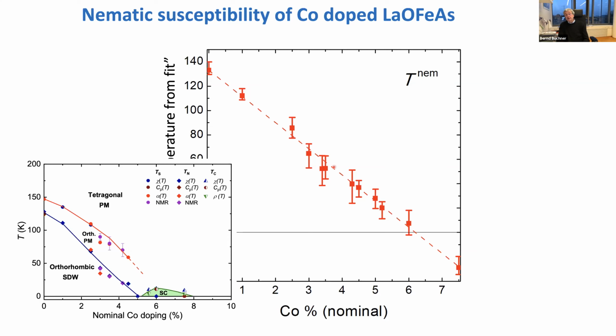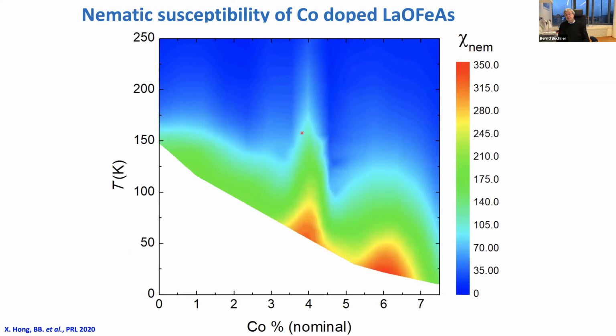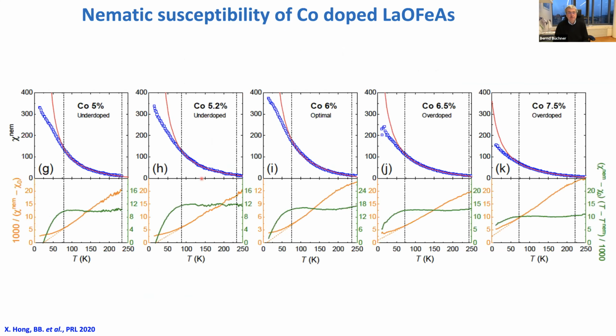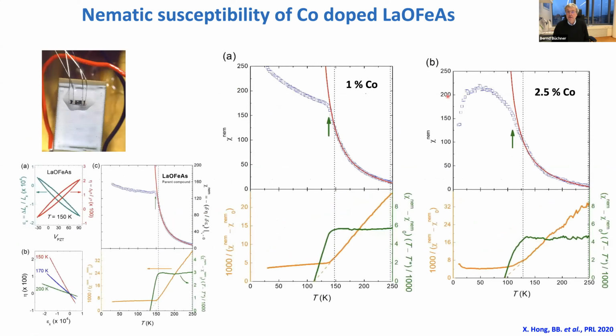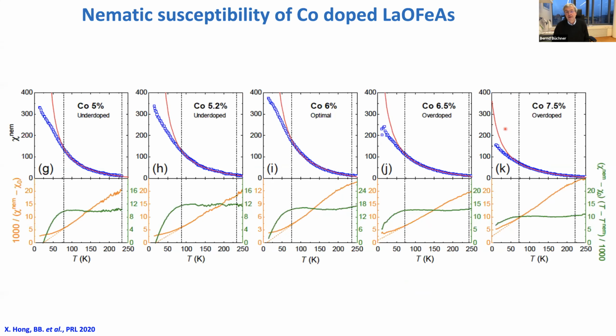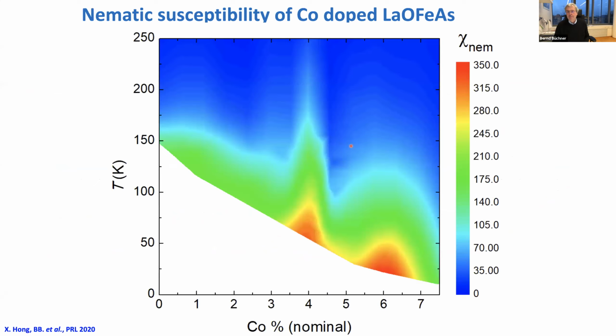But we can not only look at the nematic transition temperature, we can also look at the susceptibility. What I've plotted here is just the absolute value of the strain derivative. It's raw data, nothing is done with that. At optimal doping we have a pretty large number, so there's a very strong change of the resistivity as a function of strain. If you go to overdoping, it becomes much smaller, and if you go to underdoping, it also becomes much smaller. It also becomes smaller when you go to the parent compounds or to the strongly overdoped compounds. So without any manipulation, you just take the raw data and plot it as a function of doping, and you end up with this diagram.